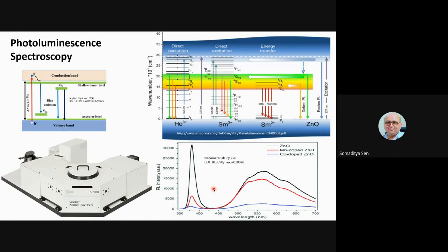Okay, what will happen? There will be oxygen defects in the lattice. And when you have oxygen defects in the lattice, that will definitely not remain as such. It will also give you some zinc defects, because it has to compensate the charge somehow, right? The lattice cannot be charged, right?